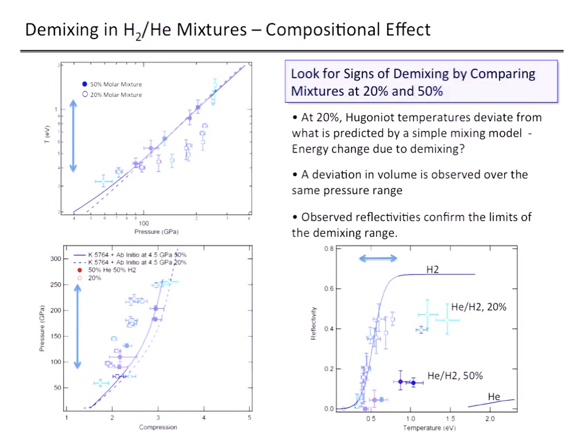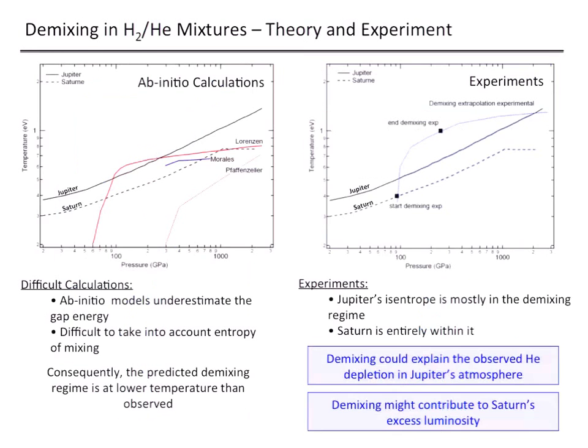If they're separating, we expect the most reflective component to dominate the reflectivity measurement. So we expect to measure predominantly the reflectivity of hydrogen, which is what we measure between about 0.4 and 0.8 eV in temperature. This gives us both pressure bounds and temperature bounds for where these materials might be demixing for a given composition.